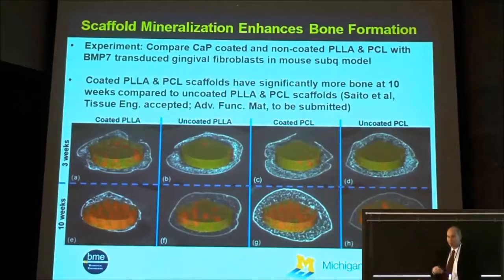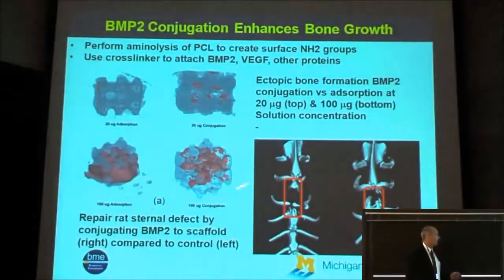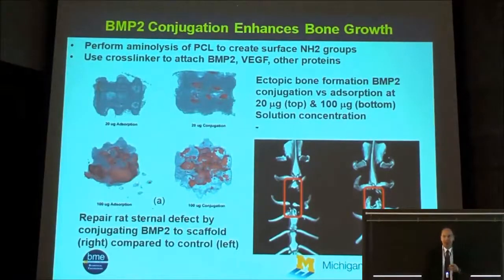Again, that's an intuitive result, but it tells us the importance of doing this modular processing and being able to functionalize scaffolds after we make them. This is the same idea of putting BMP2, conjugating it to PCL in different quantities directly to the PCL versus absorbing it. We still get a lot of bone growth either way. This is an immunocompromised model. But conjugating it, so the way that we attach the growth factor, the protein, to the scaffold, gives us more control over the location of the bone growth. And this is just putting scaffolds without BMP2 and with BMP2 in a 3-millimeter rat sternal defect. And again, you can see, obviously, it's intuitive, but being able to deliver this in controlled scaffolds helps us to regenerate tissue.